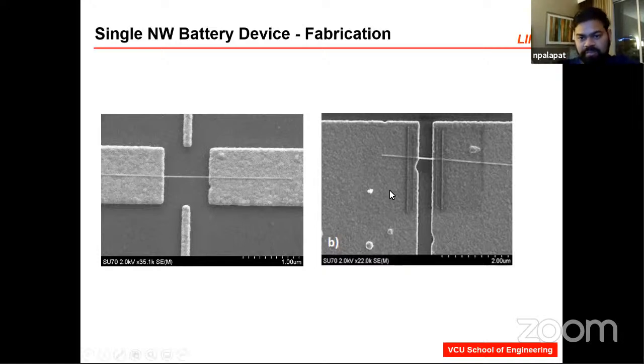Now there are some horizontal bars that you see. This is another characterization technique that I've used. It's called EBID, electron beam induced deposition. There are a couple of things that these vertical or perpendicular lines do. One is to hold the nanowire in place in the same location. The other is to provide electrical contact of the nanowire to the surface. I'll talk further in detail regarding this.